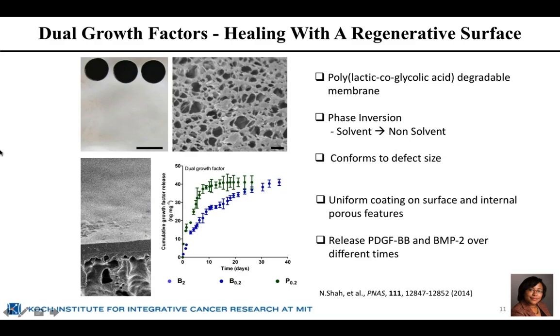So here is an SEM image showing the porous scaffold in close-up and our layer by layer film on top of it. And what you can see on the right is the release profile that we got when we essentially introduced BMP2 layers of this layer by layer film, and then introduced these platelet-derived growth factor, or PDGF, layer by layer films on top. So BMP2, as you recall, is the bone-generating growth factor. The top is the PDGF, which is going to help build the vascular system.